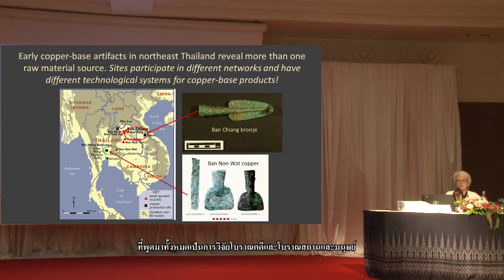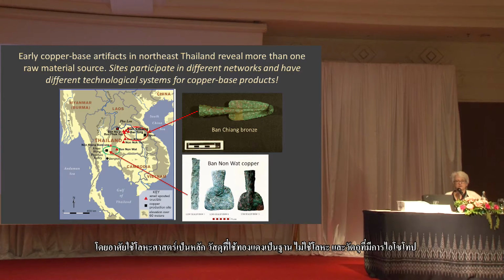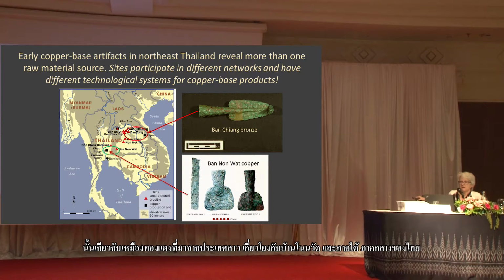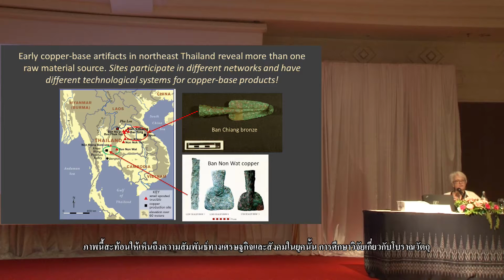Now this is to clarify how important this is. Similar work done from Ban Non Wat. First of all, at Ban Non Wat, the early copper-based objects were not tin bronze. The sample is very small, but the small sample that has been studied shows that they were copper, not alloys. And the few that have lead isotope signatures that can be related to a copper mine come from the Khao Wong Prachan Valley area. So what we are getting is a fascinating picture of how the Sakon Nakhon Basin was relating to a different copper source than Ban Non Wat and the southern northeast Thailand to central Thailand. So this is just the beginning of a picture of the social networks, the economic networks, the technological networks are much more complicated, and much more interesting than we had thought going into this.